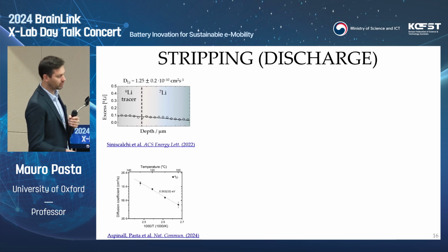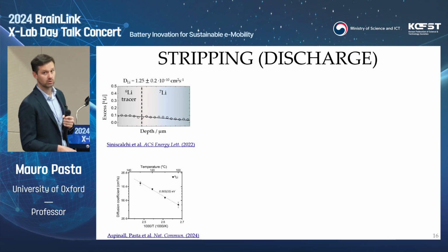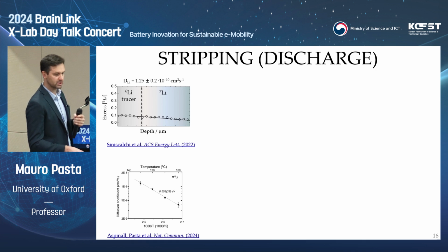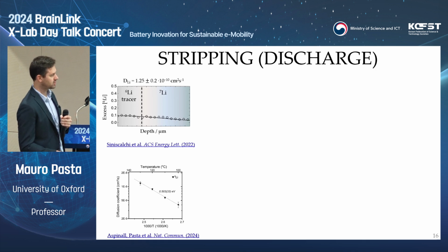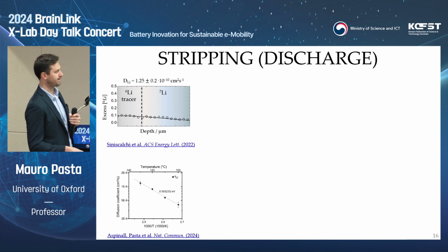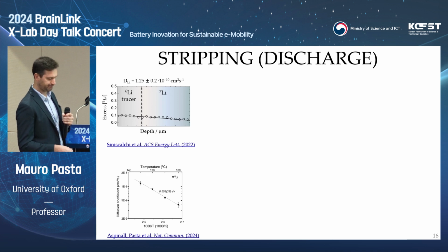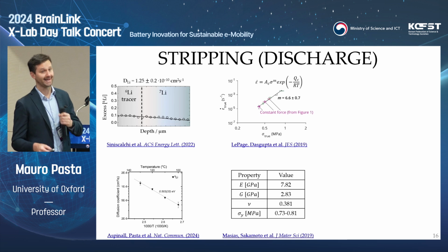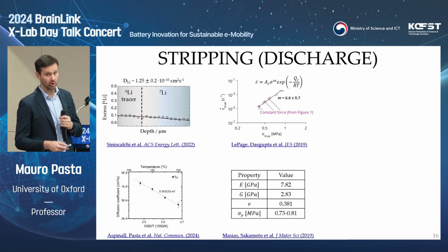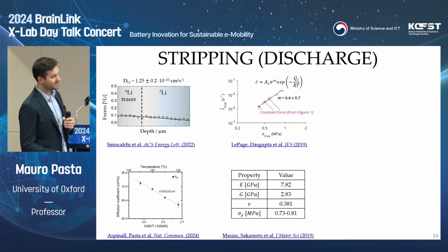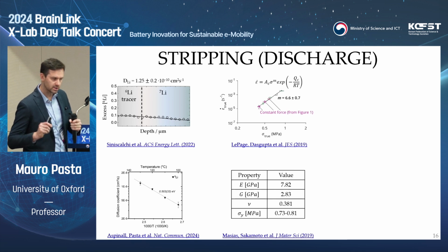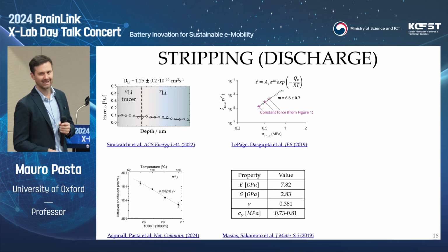Then we also cross-validated with solid-state NMR, again lithium-6 solid-state NMR, mostly because lithium-7 is quadrupolar and diffusivity is quite low. That helped us build this activation energy line and therefore extract diffusivity as a function of temperature. So you can rely on vacancy diffusivities, or in the case of lithium, you can also rely on its mechanical properties. As I mentioned earlier, the melting point is quite low. Lithium is quite soft, so its yield strength,